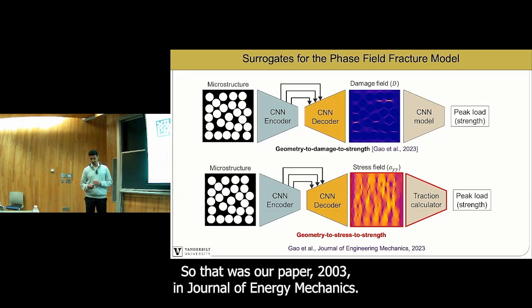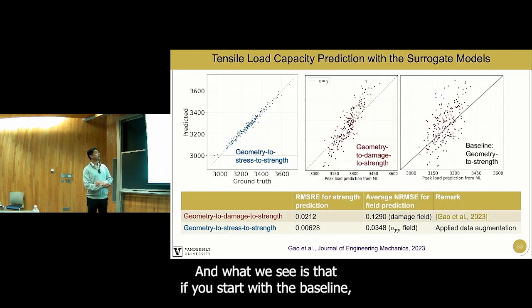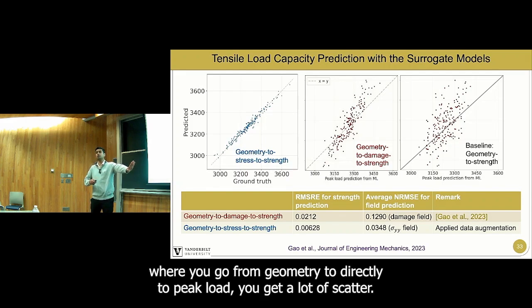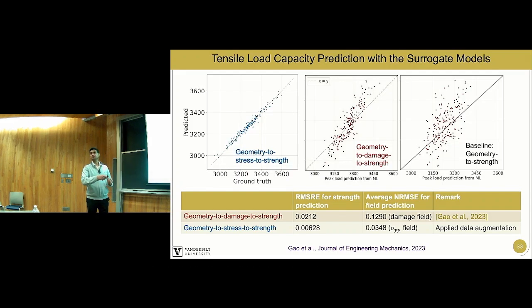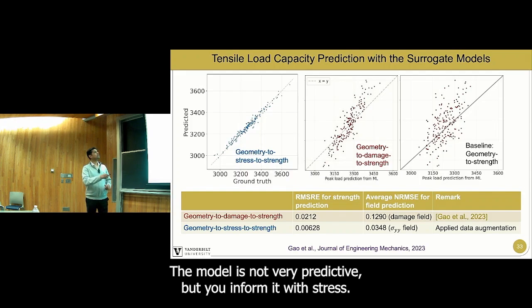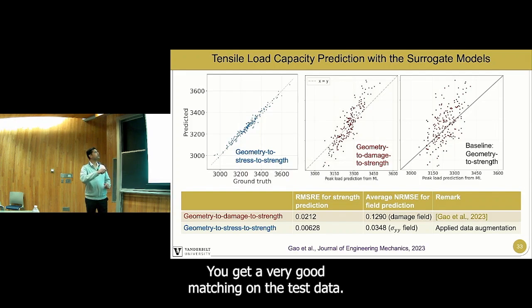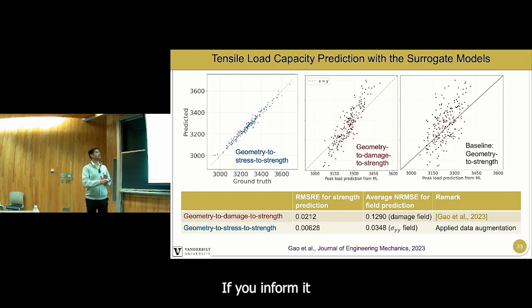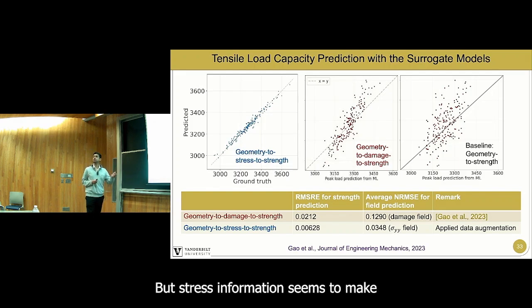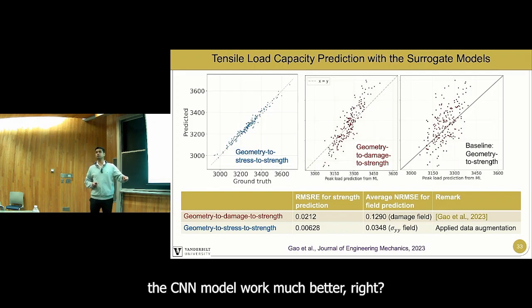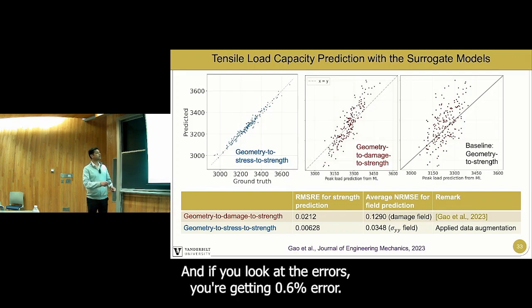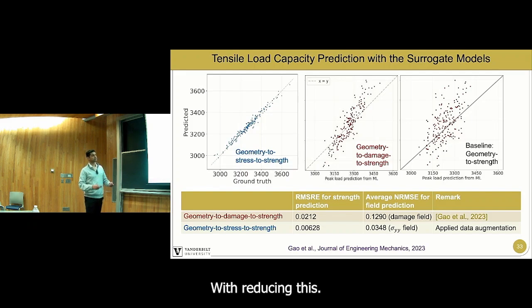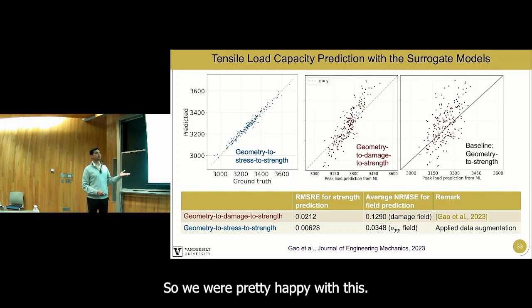So that was our 2023 paper in the Journal of Engineering Mechanics. And what we see is that if you start with the baseline, where you go from geometry directly to peak load, you get a lot of scatter. The model is not very predictive. But if you inform it with stress, you get a very good matching on the test data. If you inform it with damage, it's better than before, but stress information seems to make the CNN model work much better, right? And if you look at the errors, you're getting 0.6% error. So we were pretty happy with this.